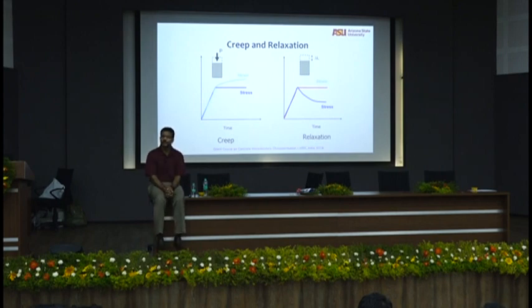Did I tell you the story with the nuclear reactor, where very high creep happened? Right? A very massive structure with extremely high creep, where cutting of a small portion of the concrete dome created random cracking all through because of creep. It was very high strength concrete, and there was so much of pumped up stresses. When you started to relax it by certain cutting, it just massively spread like crazy. It had so much stress built in. Again, an issue with high stress.